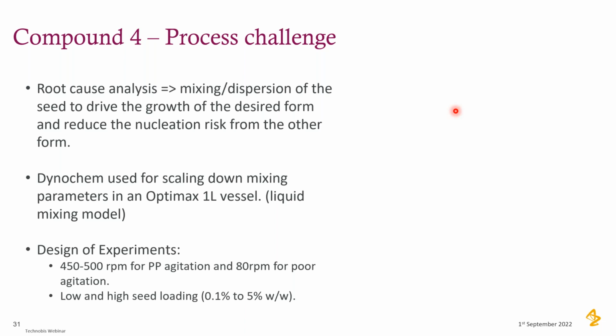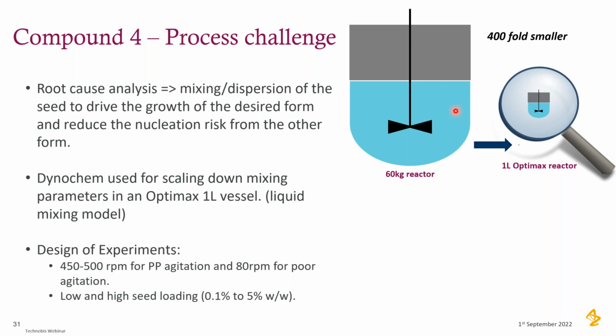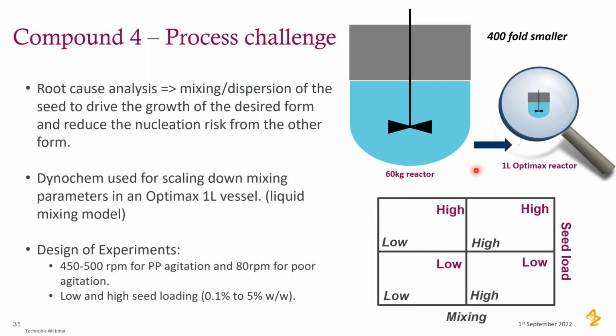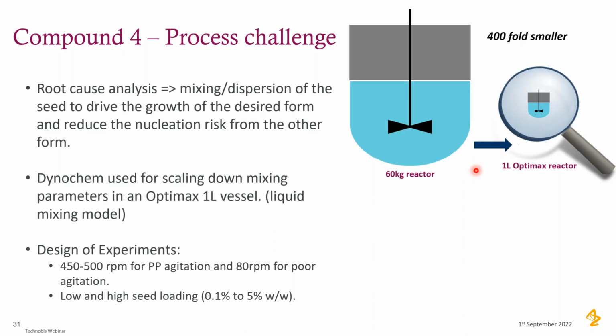So what we did is we took the tools of DynoChem and scaled down from 60 kilogram to a 1 liter Optimax reactor. So this time it is 400-fold smaller. So you can't see it, but here is basically the Optimax. So in a picture way, it's very tiny. And we used a liquid mixing model in DynoChem just to see if we can make basically a mixing scale down.